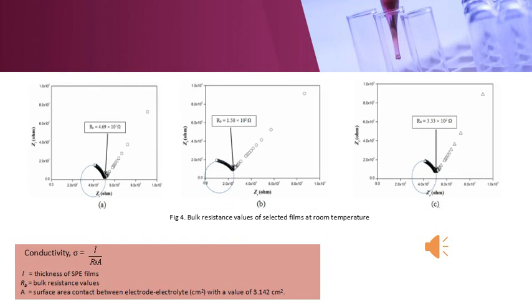Figure 4 shows the bulk resistance values of selected films at room temperature, and how to know the position of the bulk resistance. This is because the conduction mechanism is important to calculate the value of conductivity, for which one of the important formulas uses the bulk resistance. The bulk resistance is important for the technique applied at various frequencies to investigate the mechanism of ion transport and also the charge transfer in both the electrode and the electrolyte.